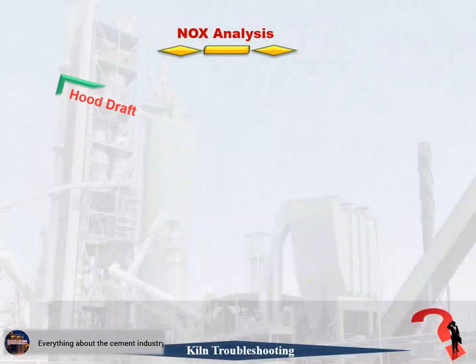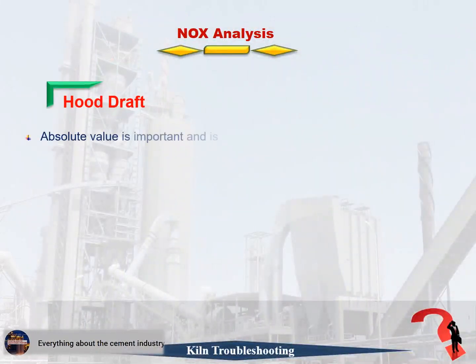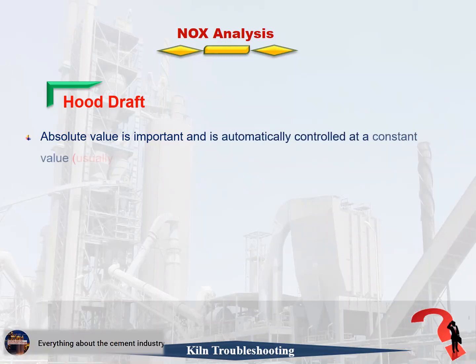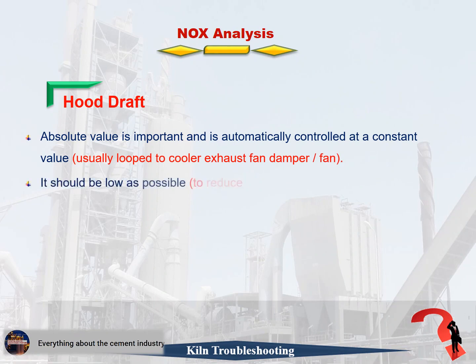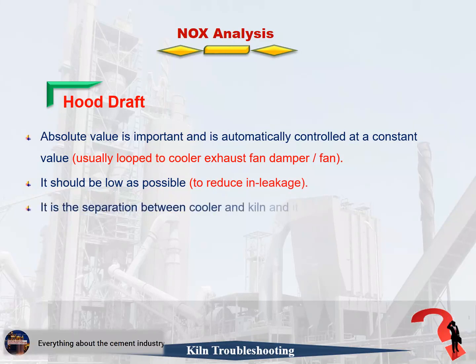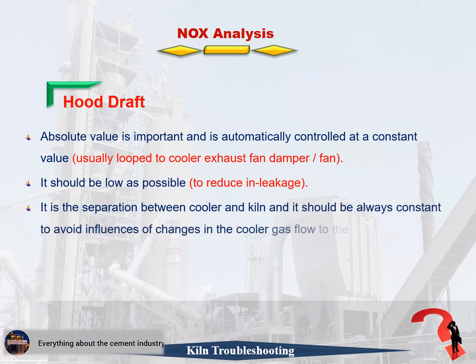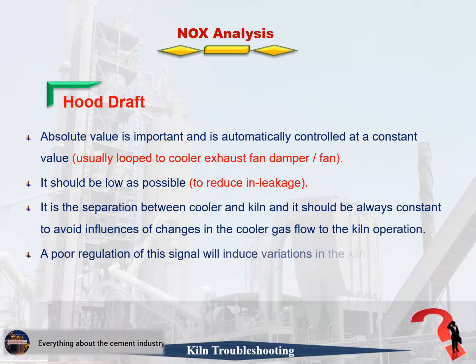Hood draft. Absolute value is important and is automatically controlled at a constant value, usually looped to the cooler exhaust fan damper or fan. It should be as low as possible, to reduce in-leakage. It is the separation between cooler and kiln, and it should always be constant to avoid influences of changes in the cooler gas flow on the kiln operation. A poor regulation of the signal will induce variations in the kiln gas flow, and could bring the kiln into cycling.